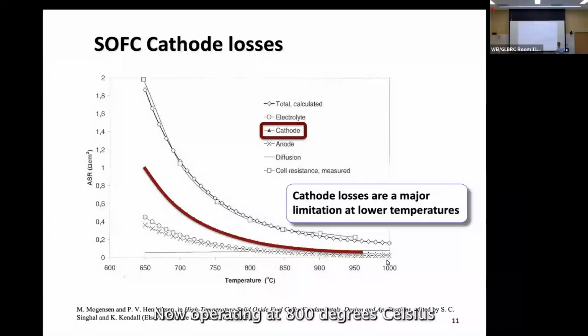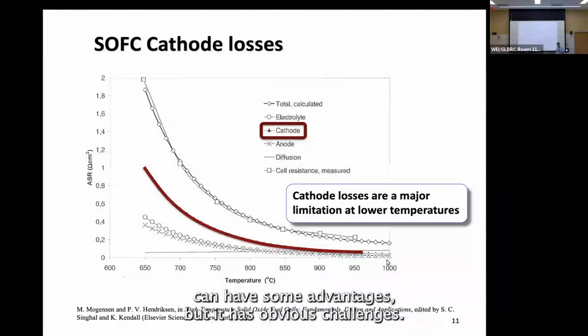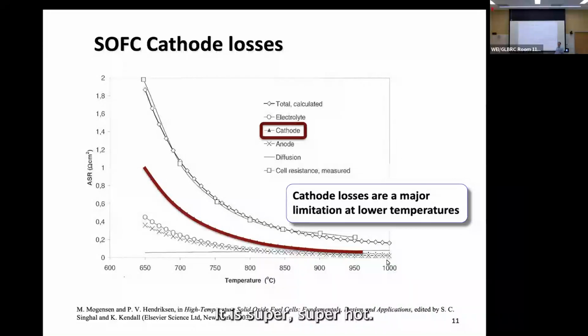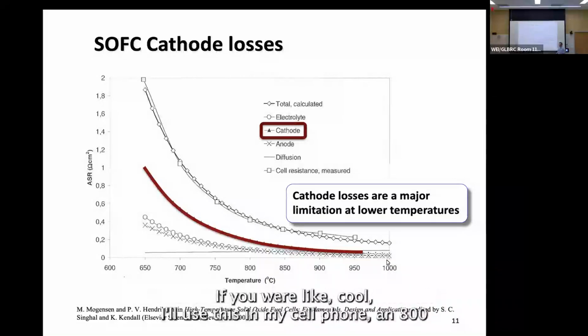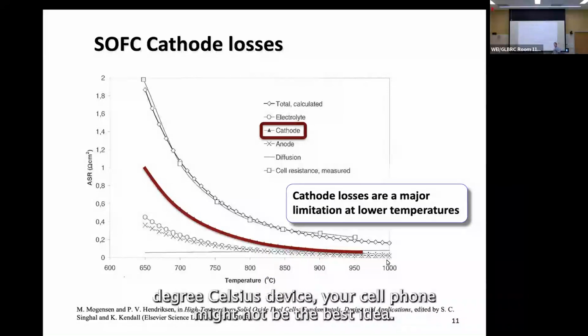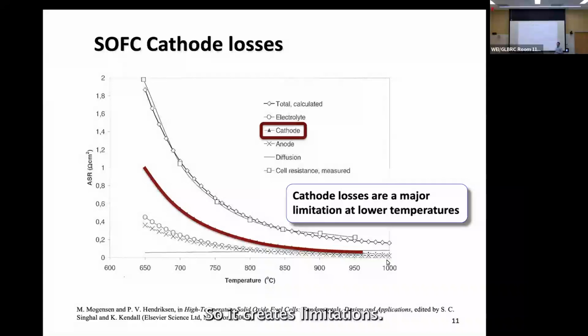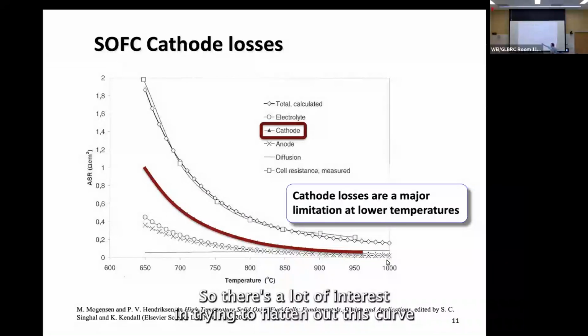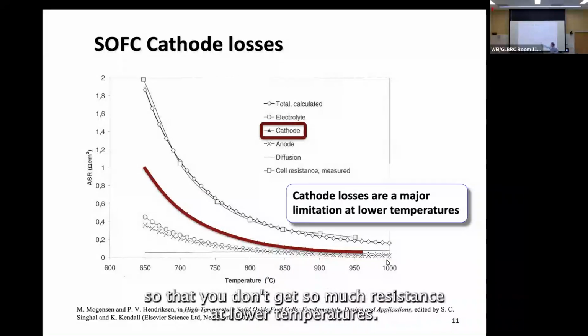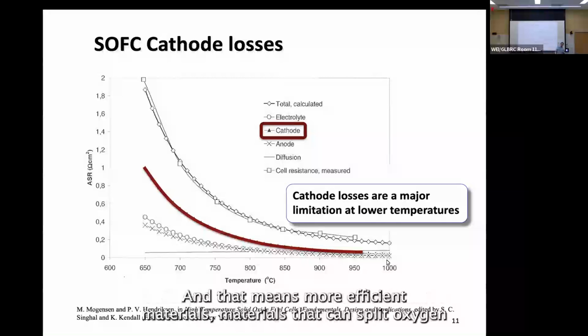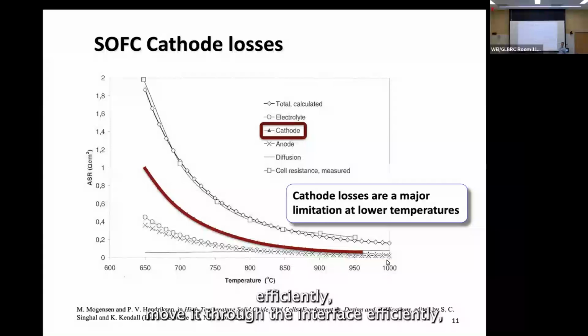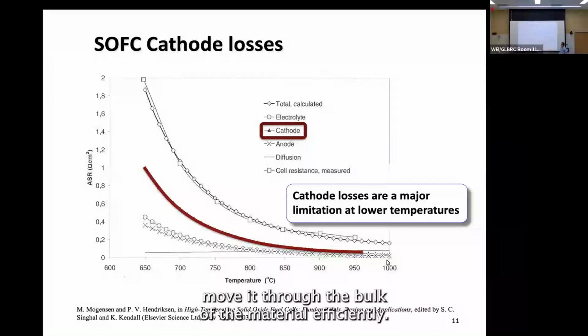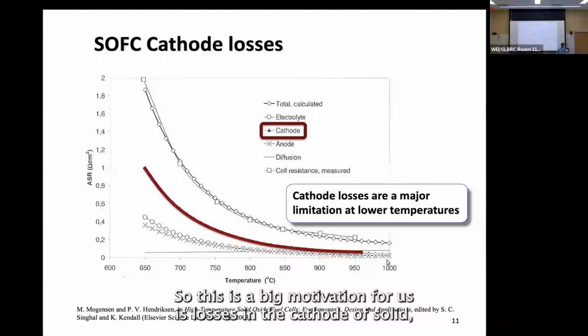Now, operating at 800 degrees Celsius can have some advantages, but it has obvious challenges. It is super, super hot. You're going to have a lot of materials degradation. If you were like, oh, cool, I'll use this in my cell phone, an 800 degrees Celsius device in your cell phone might not be the best idea. So it creates limitations. So there's a lot of interest in trying to flatten out this curve so that you don't get so much resistance down at lower temperatures. And that means more efficient materials, materials that can split oxygen efficiently, move it through the interface efficiently, move it through the bulk of the material efficiently. So this is a big motivation for us, is losses in the cathode of solid oxide fuel cells.